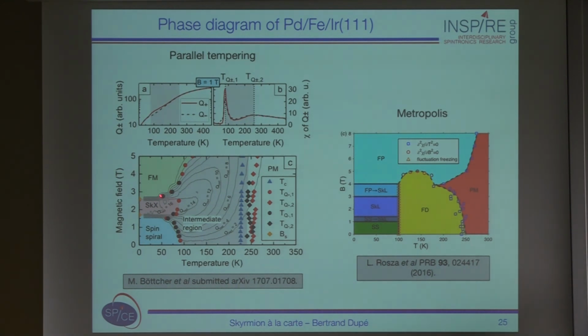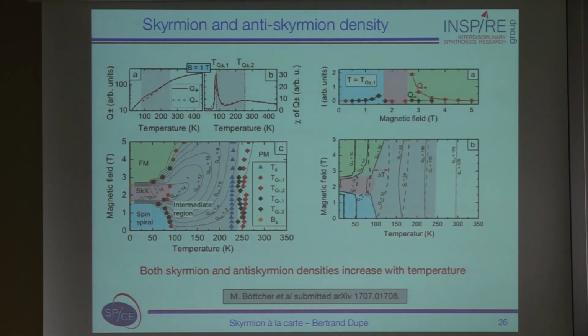You see that in this region here, in the colored region, the topological charge is almost constant. So as soon as you are here, you don't change the number of skyrmions anymore. When you change into this gray shaded area, your number of skyrmions can change, and as you increase the temperature, of course, you start to have less and less skyrmions. So now if you plot this information, the skyrmion and anti-skyrmion density as a function of temperature, you get the graph on the right, which I show here.